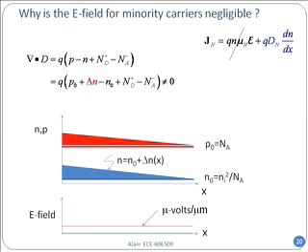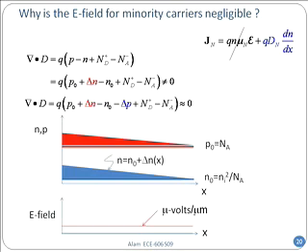Now, do you see here that this region is almost charge neutral at every point, but it's not density neutral at every point. The density is no longer the same, right? At every point, density is non-uniform, but charge-wise, it's essentially more or less the same. And as a result, that delta P flowing in from the contact is almost equal to 0.